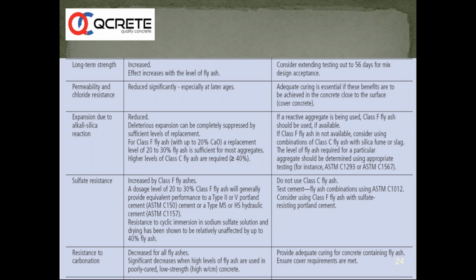Also, we need to cure the concrete properly. If we don't cure fly ash concrete properly, and if we don't provide a proper cover to concrete made with fly ash, we will have problems which can be detrimental, especially from the point of view of carbonation. So we need to be careful about the carbonation effect. For that, we need increased curing when we are talking about fly ash incorporated concretes vis-a-vis OPC mix. And cover also has to be increased when we are talking about fly ash incorporated concretes.